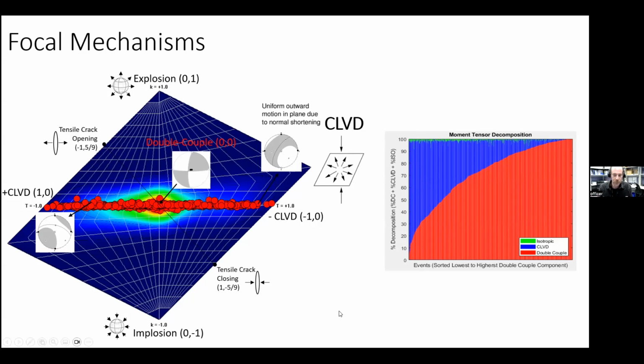And this is significant because at low pressure, in order to generate fracture, you first need to open cracks. So tensile cracks fall right on this line here, but we don't see any tensile cracks. You always do at low pressure. That's how things break: first you open cracks, then they link up. But because we're under pressure, we can't open cracks. So we have mostly shear. I think all shear, and I'll say why in a minute.